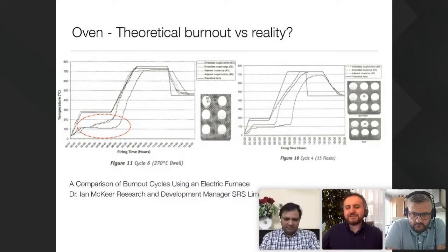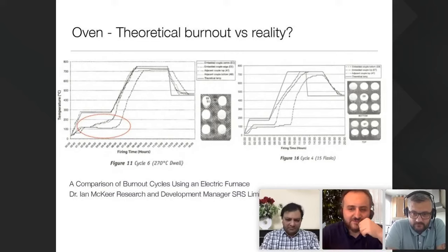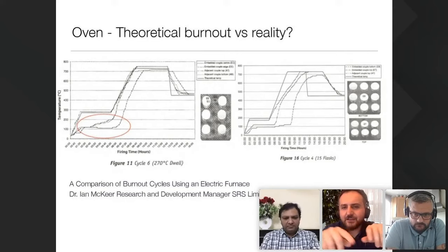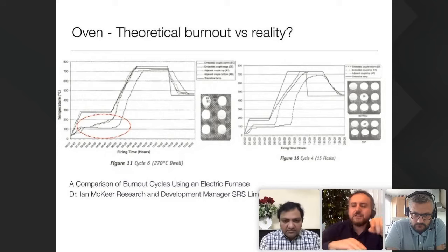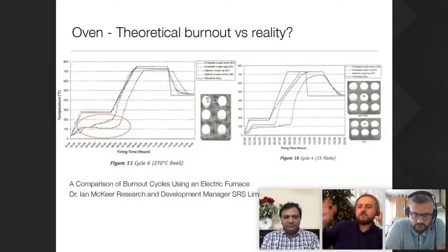Exactly. But even if you do it very fast, that flask will still remain at 100, 120 degrees, whatever you do, right? The other interesting thing on the right-hand side is, as you can see, even if you cut your burnout - let's say you go from 700 degrees to 450 degrees - due to the hysteresis and due to the fact that the investment is like an insulator of heat.